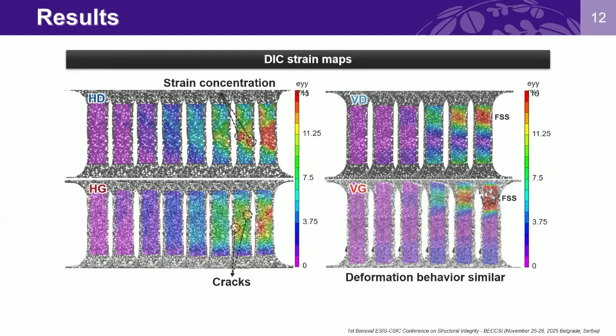Moreover, in situ DIC was performed to monitor strain localization during the tensile test. We can find that the strain concentration tends to generate from the two sides and spread to the whole gauge dimension in HD, while the cracks always initiate at a relatively lower level of strain in HG. Both VD and VG exhibit similar deformation behavior, with the higher strain zone located at the ferritic stainless steel region.